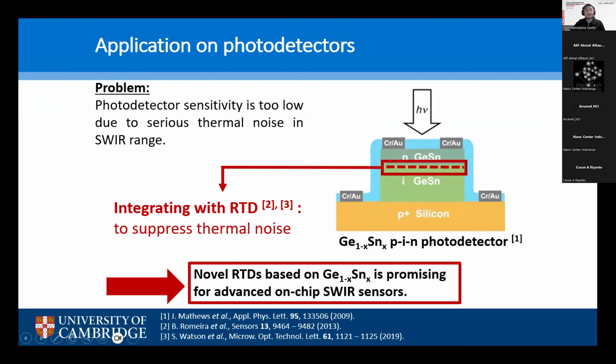Okay, so the issue is that photodetector sensitivity is too low due to serious thermal noise in the SWIR range. And that's because of the low band gap nature of germanium tin, so it's prone to thermal noise. For example, with germanium tin, you would get responsivity of not more than 0.1 ampere per watt. So to suppress this, we need to integrate a resonant tunneling diode with a photodetector based on germanium tin to tackle this kind of problem.